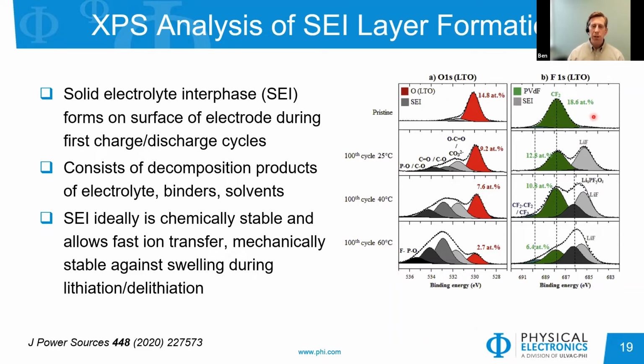And so what we are showing here that we can use XPS for is to look at essentially a pristine material. This is a lithium titanate material. And with pristine, we essentially are seeing carbon fluorine type bonding. This would be our fluorine 1s region. And in our oxygen 1s, we see the oxygen mostly from the titanate. After we cycle 100 times, we do see emergence of a lithium fluoride type species, which is one of the decomposition products. And depending on the temperature that was used for these cycling studies, we can see different products emerging. And so we can then look at that as a function of the performance of the battery to understand which chemical component is maybe restricting my performance, and then optimize your battery that way.